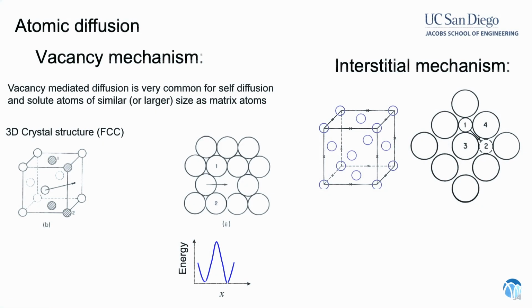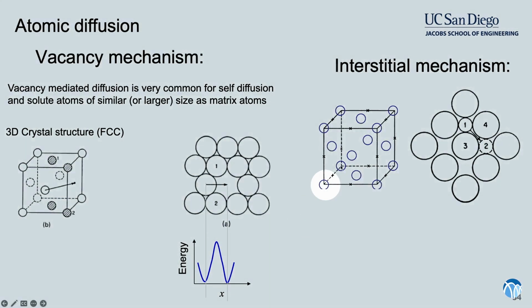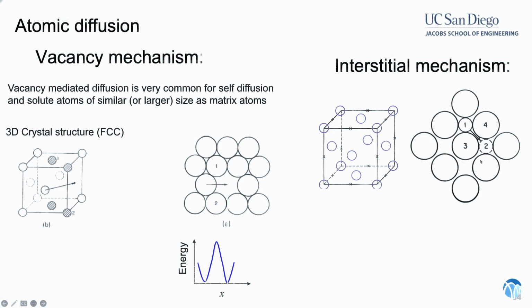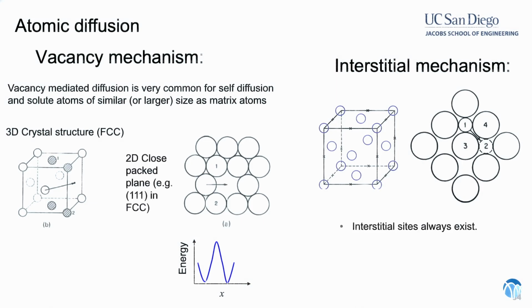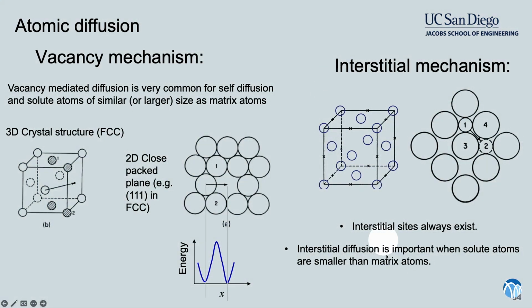This is an interstitial mechanism, and this is important because interstitial sites are always there. So it's always very easy to move amongst these interstitial in-between equilibrium atom sites. And this is how hydrogen moves in metals. So again, hydrogen is the fuel. So those sites are always there. So that's a diffusion mechanism that you should consider. So this interstitial diffusion is important when solute atoms, again, are smaller, like in the hydrogen case.